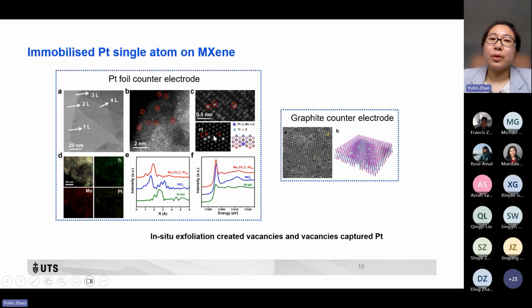catalyst. And we have also done the HAADF-STEM image simulation by removing the molybdenum atoms and putting the platinum atoms in. We see these two images are quite similar. So it should be the platinum occupying the vacancy and stabilized by the substrate.